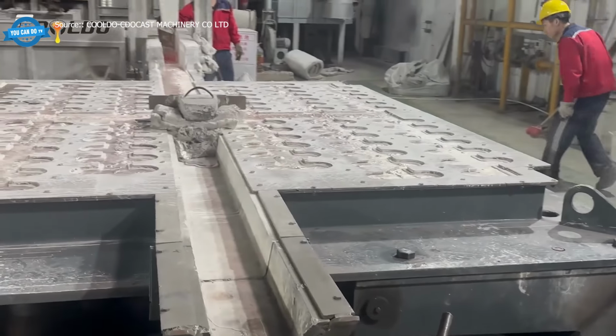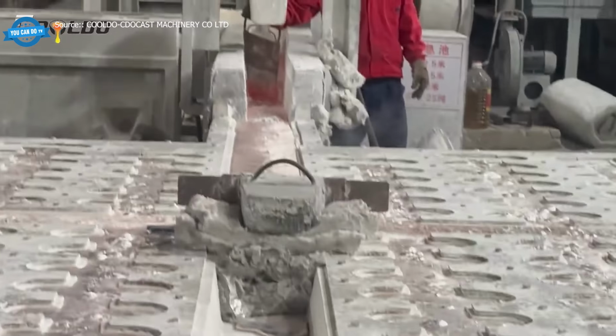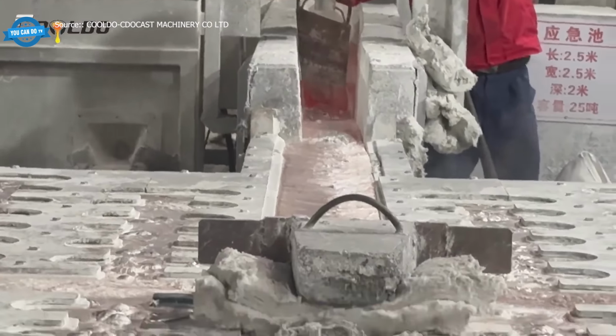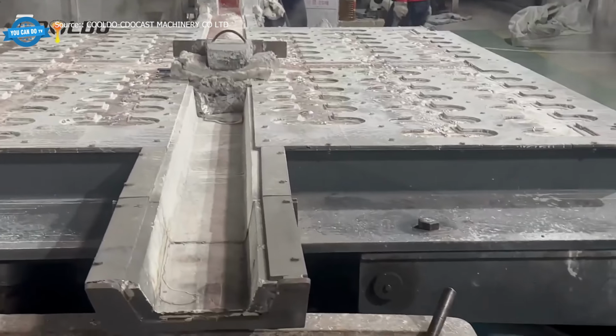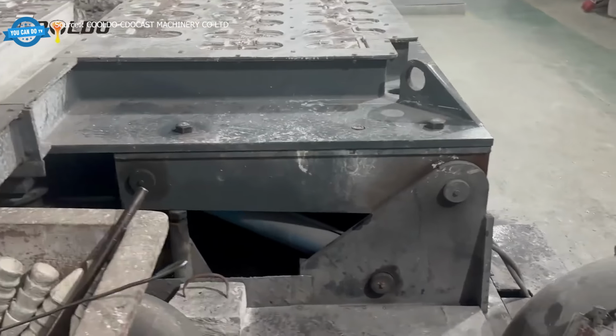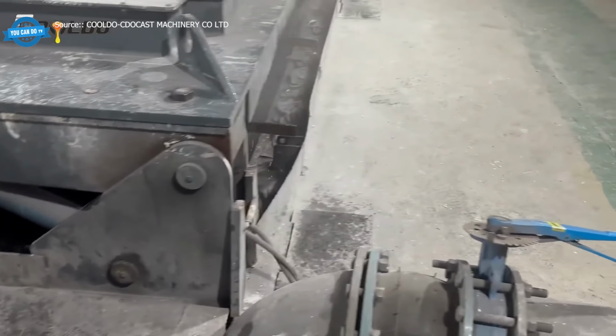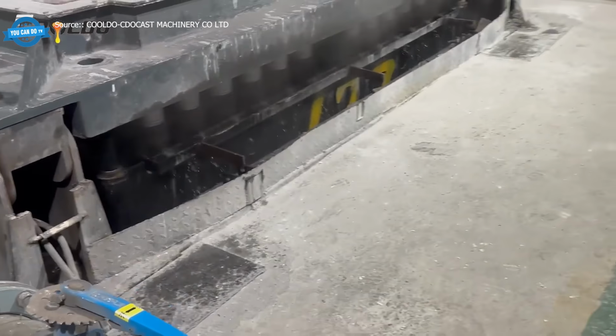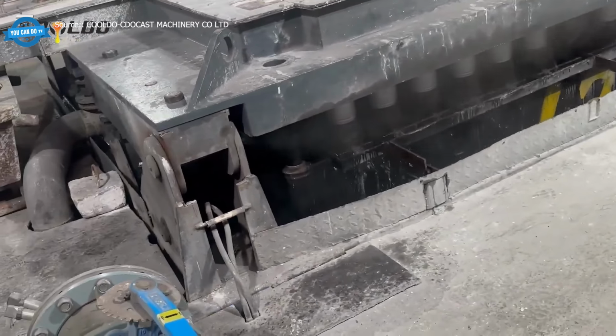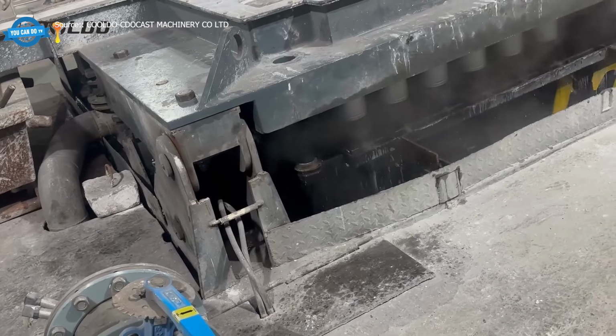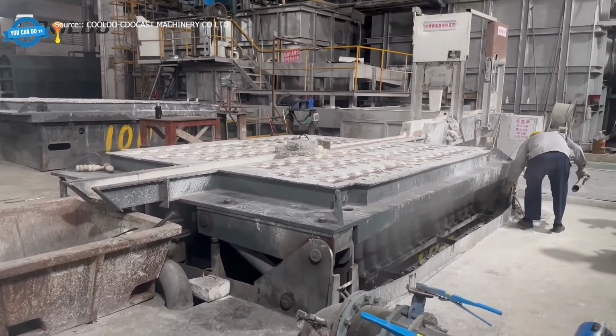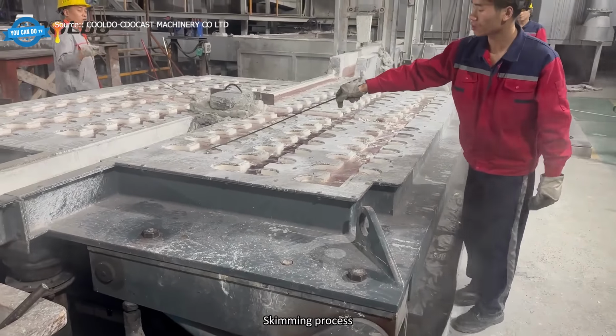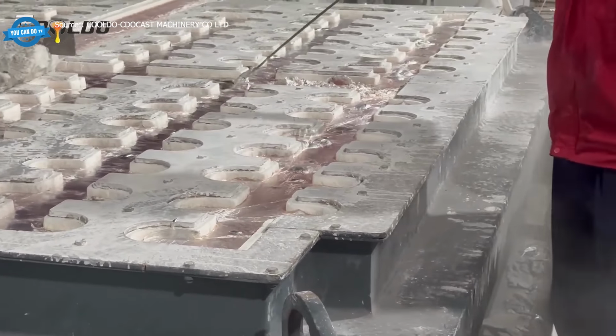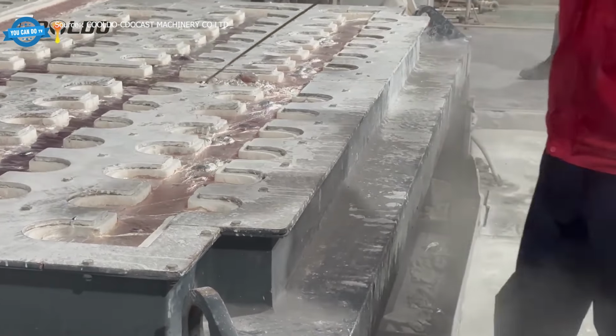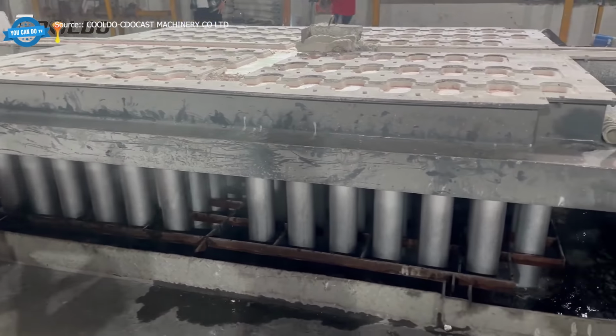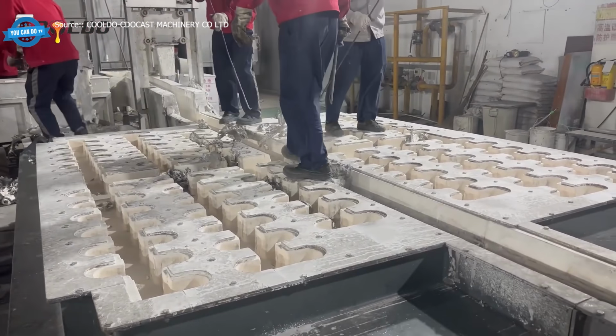Filter plates catch any solid inclusions before the metal enters the casting table. From there, molten aluminum flows through a launder into the casting molds. The billets form as the metal cools from the outside in, pulled downward at a controlled rate. A skimming process removes surface dross throughout the pour. When the billets reach full length, they're lifted out with a crane and moved to the automatic cutting machine.